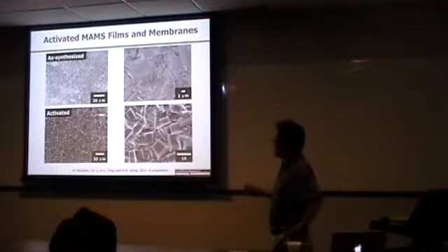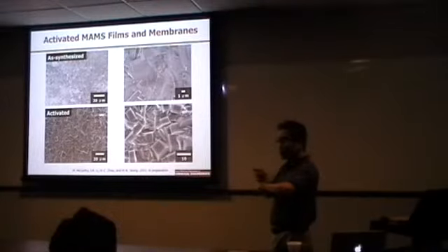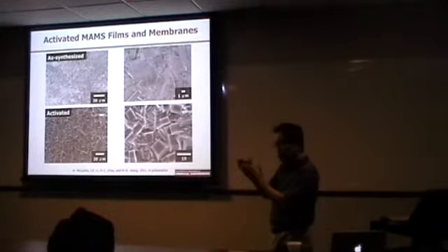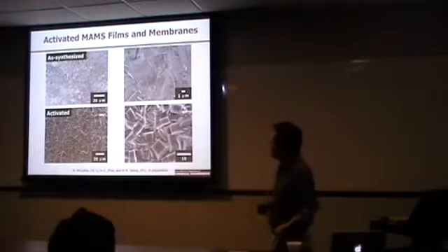This is because these MOFs are based on graphite-like layered structure, which means the interaction between the layers is not as strong. So when solvent is evaporating from the pores, it contracts, and that puts stress, and that creates cracks.